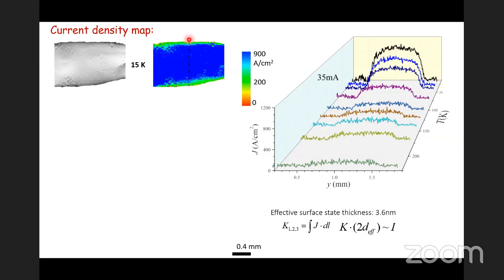If you integrate this current density across this length into the thickness, that will give you the total current which is flowing. And from this, you can get the thickness of this surface sheet to be about 3.6 nanometers. So the topological surface state on the single crystal is about 3.6 nanometers, which has been seen from other experiments also to be of this order. So we are actually looking at the conduction through a 2D surface state on the single crystal.